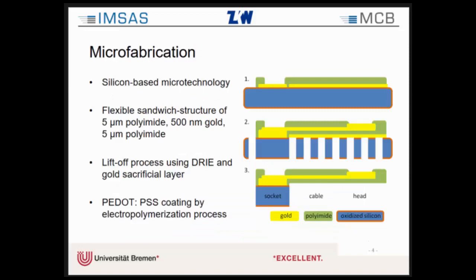So I'd like to show you briefly the microfabrication of these arrays. We use silicon-based microtechnology. We start with an oxidized silicon wafer. In the first step, we deposit and structure a gold layer, which will be used as a sacrificial layer to release the array after the fabrication. The first polyimide layer is spin-coated and structured. After that, we deposit the second gold layer to produce the conducting paths and the electrodes, and also the soldering pads.